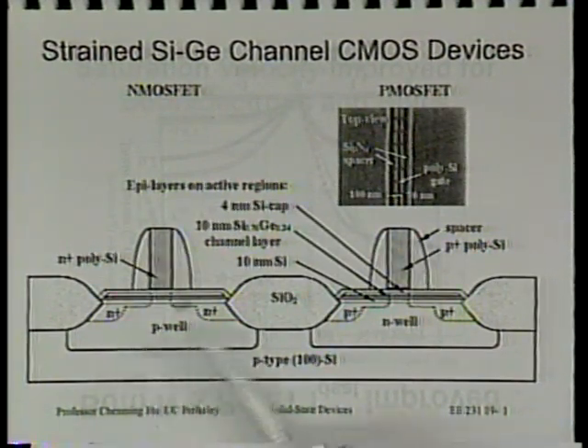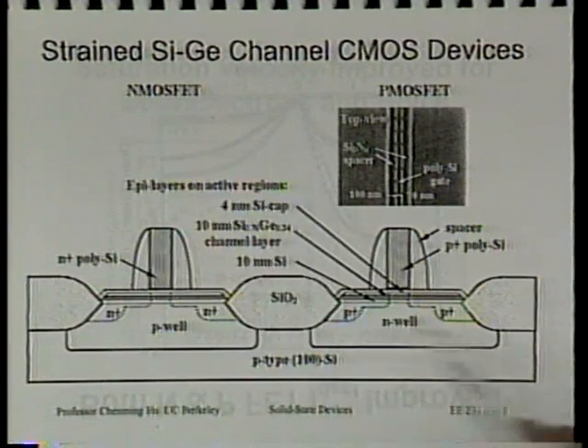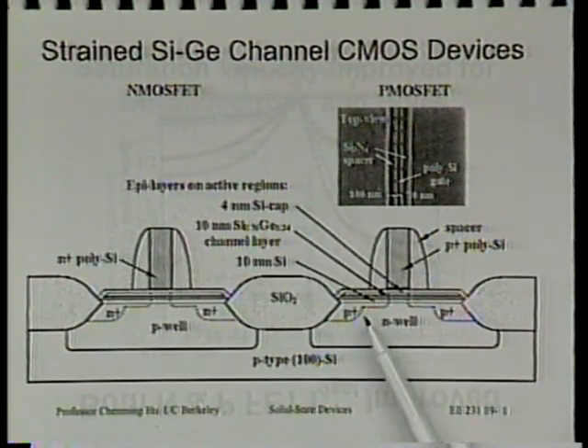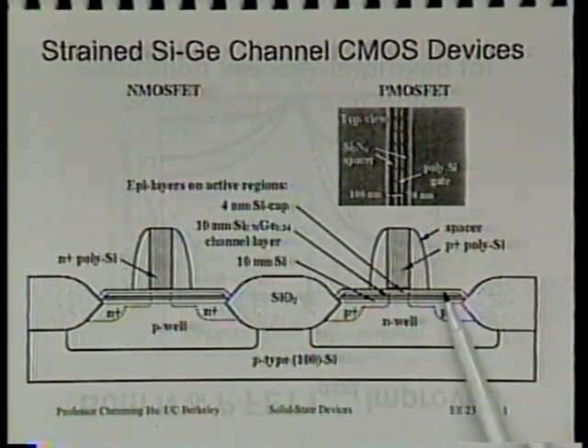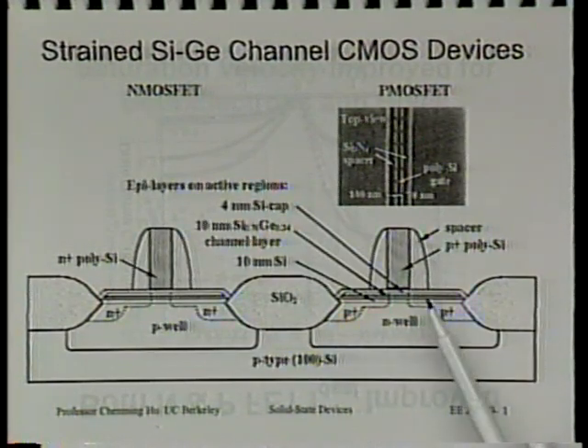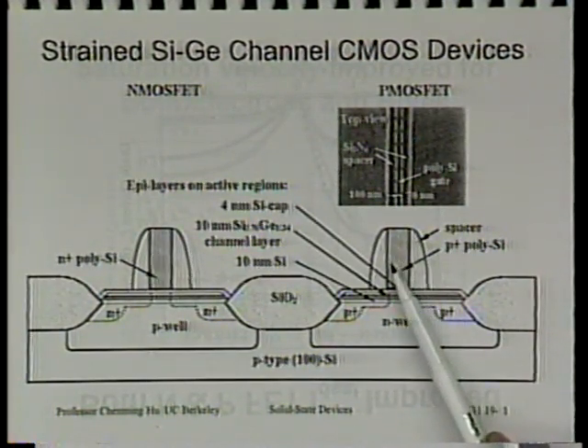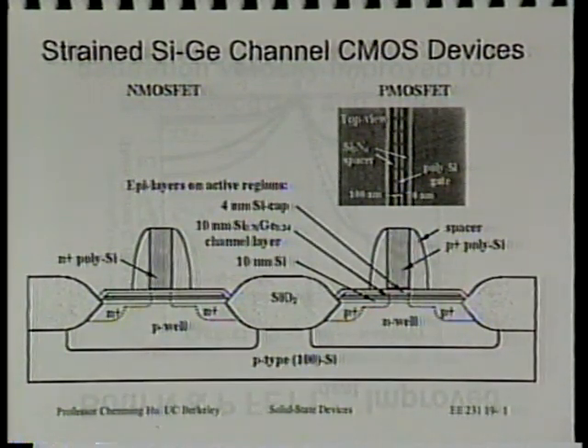Okay, so after clean, after oxidation, hopefully not much silicon is left. But still we had more than we would like to have left there. And so oxide is on top of that. Of course, SiO2 is on top of the silicon cap, and then you put down your, let's say, polysilicon gate material, etch it, do spacer, implantation, exactly the same as an ordinary CMOS process. So the only difference is we add this selective epitaxial silicon germanium. The rest will be identical to the CMOS process. All right, idea. Yes, Jane?